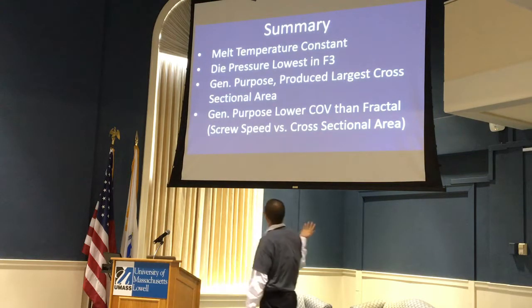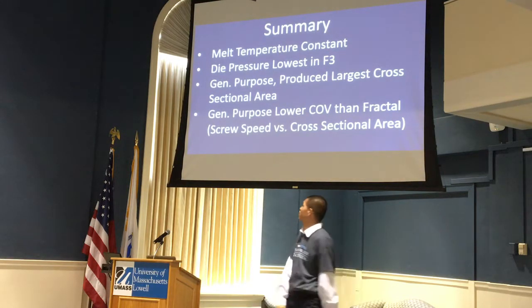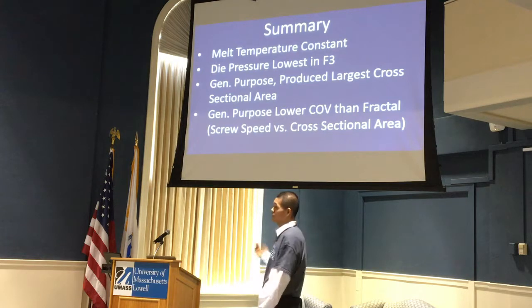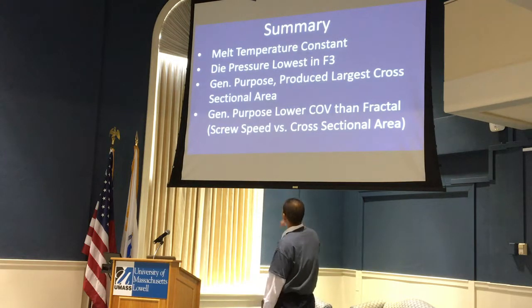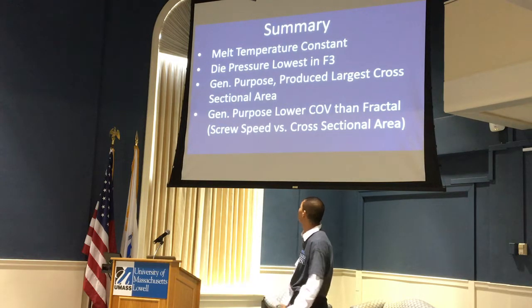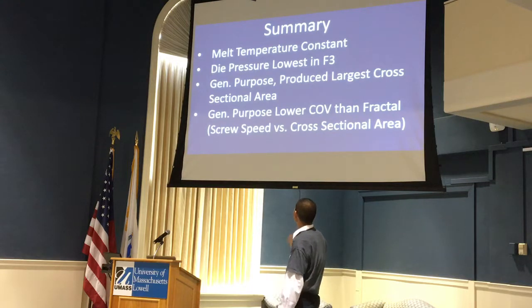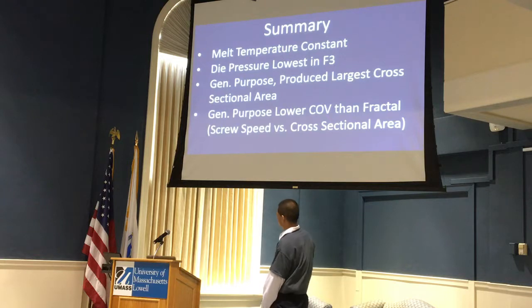So just a quick summary. Our melt temperature was constant. Our die pressure was lowest in our Fractal screw. Our general purpose screw produced the largest cross-sectional area. The general purpose screw had the lowest coefficients of variance compared to the Fractal in our screw speed versus cross-sectional area.